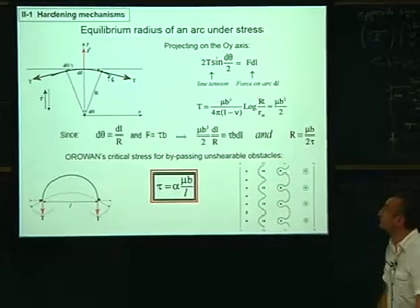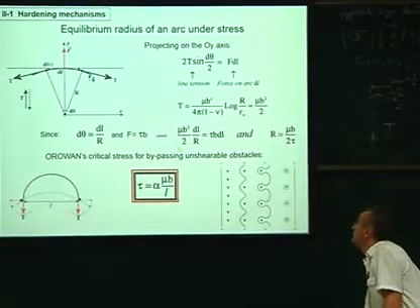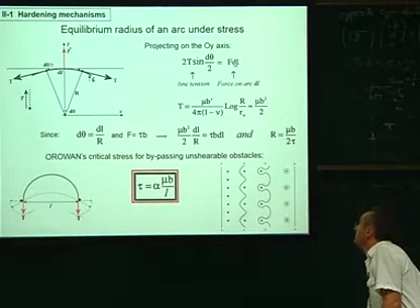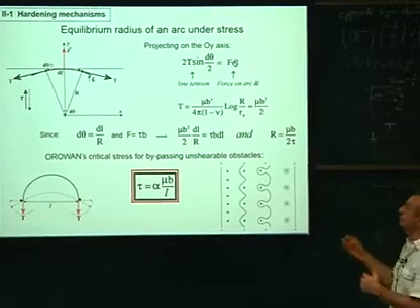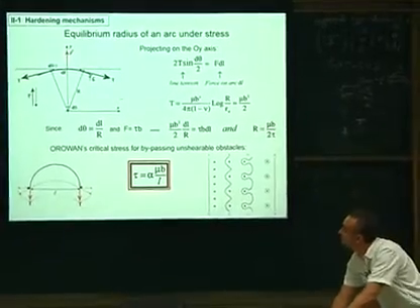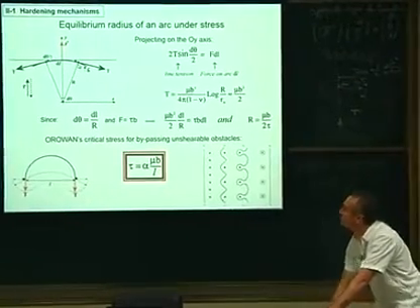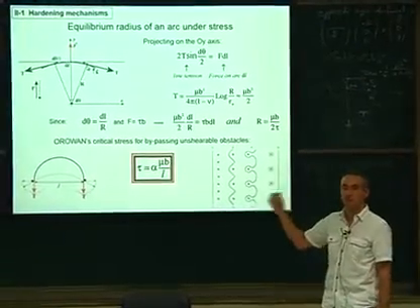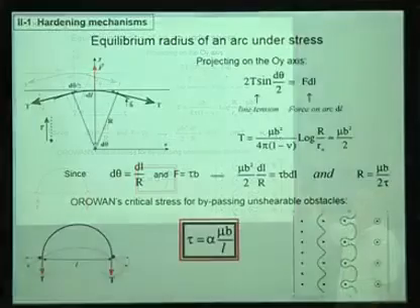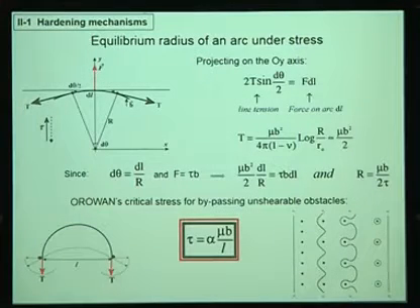If you project along the y-axis, the force F dl, the force applied on all this length, because remember that the force is per unit of length, should be compensated by the projection of the two tensile forces, which are the line tension. And that will be 2 times T sine d theta over 2. This gives the projection of this force along the y-axis.